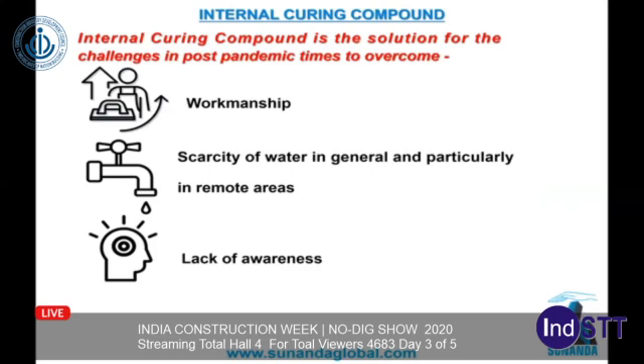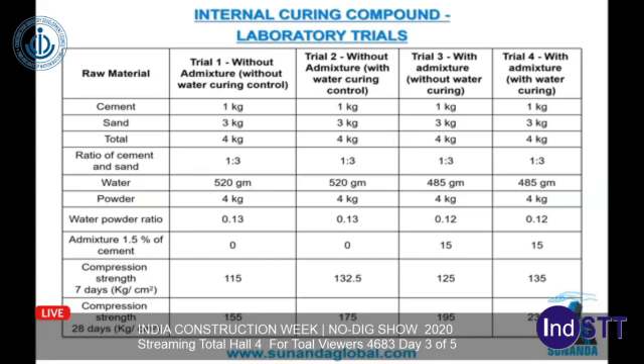Workmanship, scarcity of water, lack of awareness, need for conservation of water, all these points are very important in post-pandemic days. This table here is self-explanatory. In trial 1 we have not used any water curing compound, any water curing. In trial 2 we have used no admixture but water curing. In trial 3 we have used the internal curing admixture but without external water curing. And in trial 4 we have done water curing as well as the internal admixture.